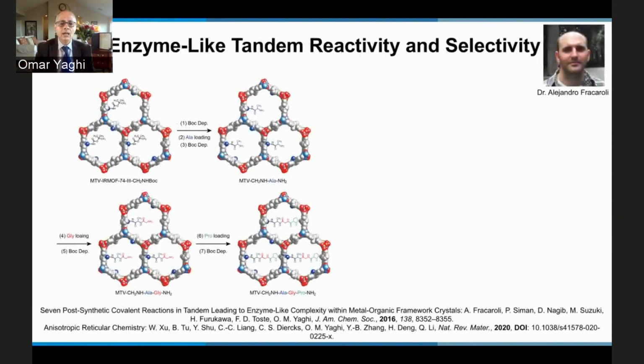So let me show you what the future offers, I think, for MOFs, at least in one direction. Since Professor Ertl is interested in catalysis, I want to share this result with you. Here we have a MOF that is made from rod SBUs that are linked by organic linkers. And we can functionalize the rods or the linkers so that they have NH2 units onto which one can add, in this case, amino acids to make a short chain amino acid peptide, a short peptide into the pores.